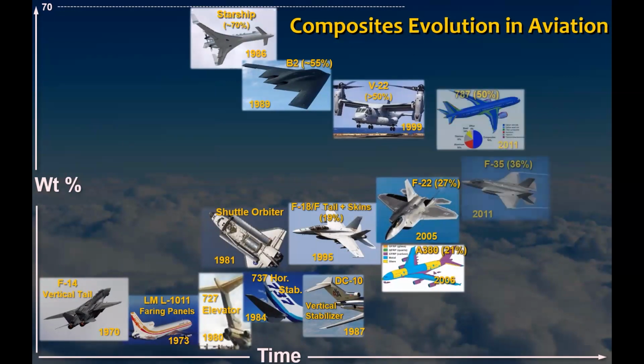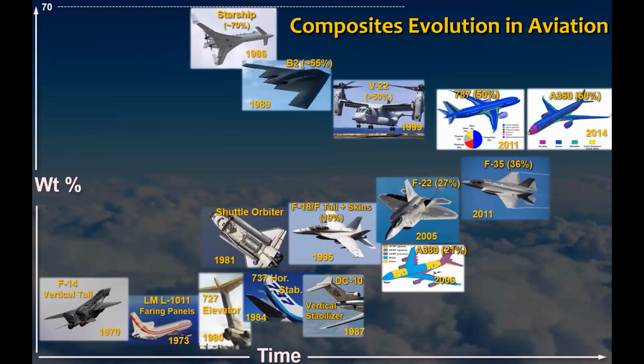As time evolves, we've gotten to the point now where we're at the 787, F-35, and the A350, getting to around 50% composites by weight. By volume, those applications are over 80% or so, but by weight we're only about 50%. The pinnacle here is the Beechcraft Starship back in the 80s, which achieved around 70%, and that had a horrendous history of problems that caused the program to retire that application.